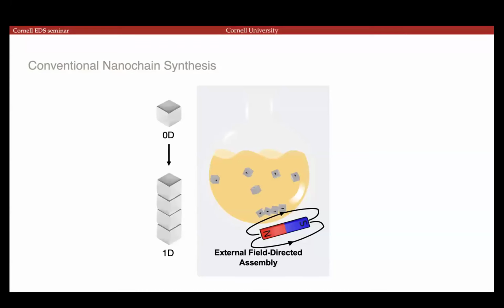And one way to improve that is by increasing the shape anisotropy and reducing the demagnetization field. So we can go from just a single particle to then a nanochain and get a higher remnant magnetization. Most of the ways people synthesize these is just applying a magnetic field during synthesis, and then the particles will align within the field.